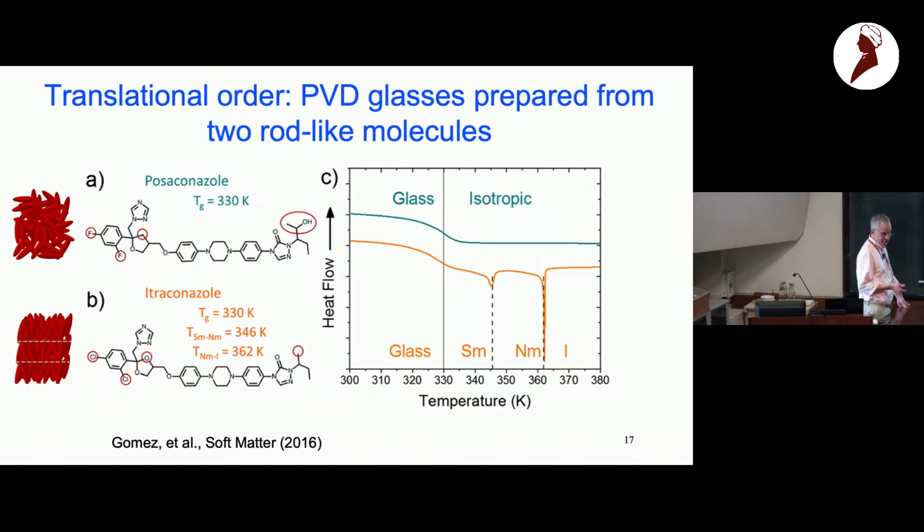So let me try and translate your question into what I was thinking. One of the possibilities we considered is that since the deposition process essentially equilibrates at a lower temperature, there is a true phase transition, in this case to a liquid crystal state, and it's just out of reach, just below the ordinary glass transition temperature, and we accessed it. I think that's a plausible interpretation of the results. We took this ordinary glass at 5 degrees below Tg and aged it for months and did not see the appearance of that, but that wouldn't, strictly speaking, rule it out.